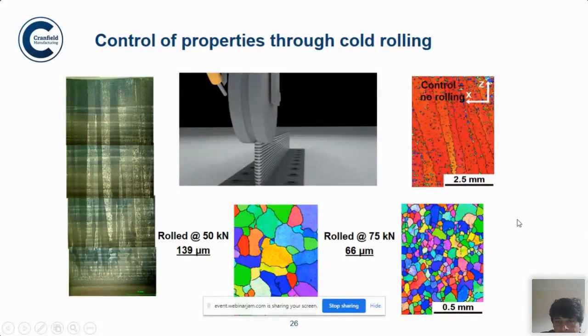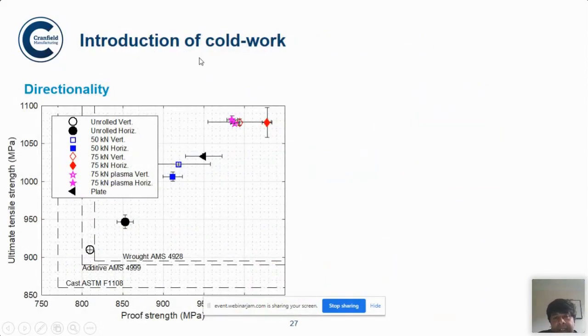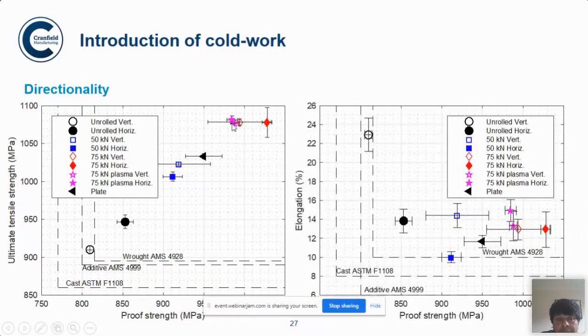So when you do this, what will happen is shown in the mechanical testing results. As you can see here, directionality, which basically means anisotropy. So in different directions, you have different properties if you have a columnar grain, and you can see this filled in black and this open circle black. They are quite widely different in terms of proof strength and tensile strength. Whereas when you roll, these are the different rolling loads that are applied, and you can see here they are almost merged. So you don't have any directionality anymore, and the properties have increased tremendously. So this black triangle is showing the plate, which is a wrought alloy. So you can create properties in the deposit which is similar strength or even higher strength than the wrought version of that particular alloy.